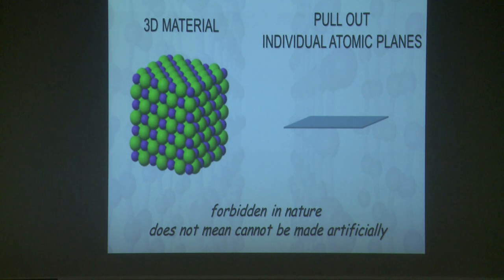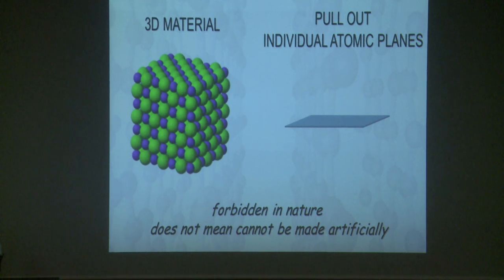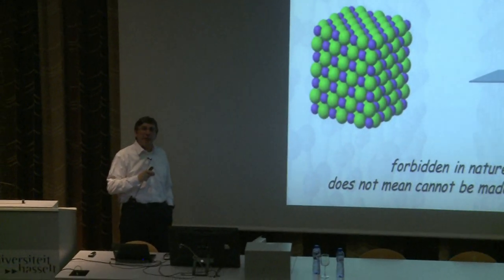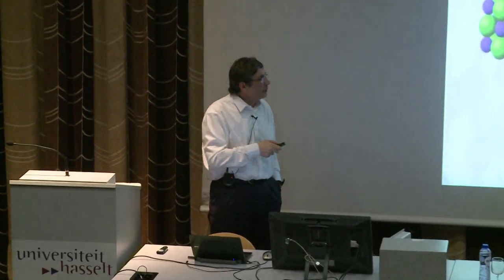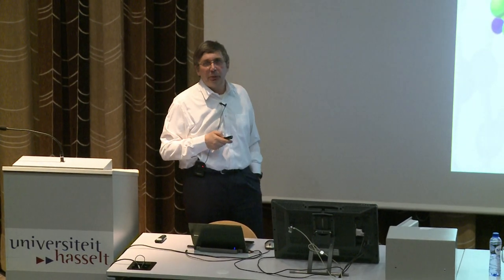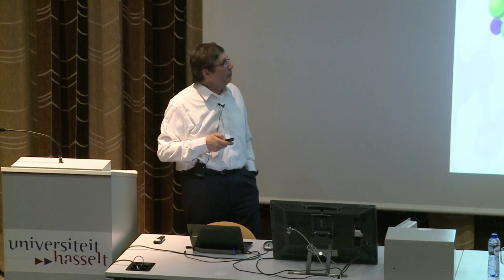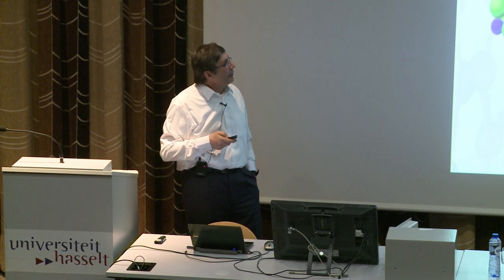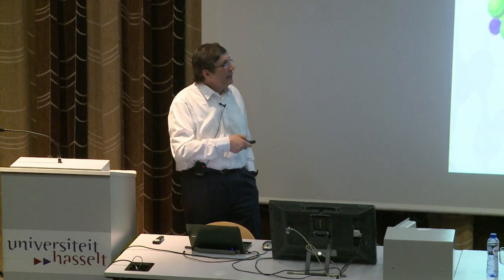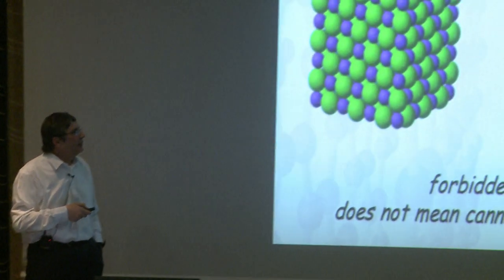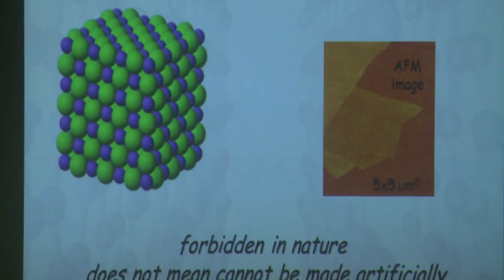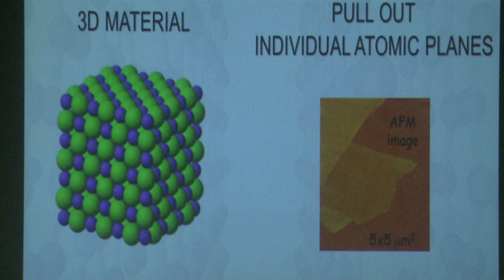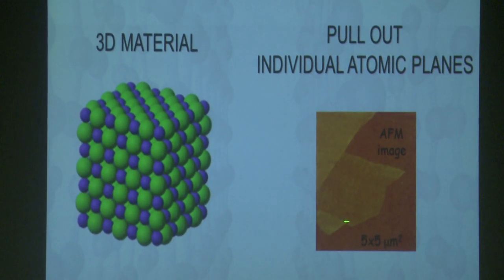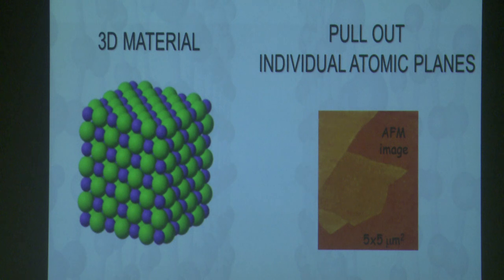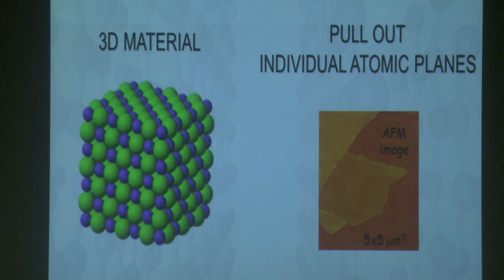That's essentially what we have done in our experiment. We take a material grown at very high temperature, cool it down to room temperature, and then extract one atomic plane. It seems to be very simple, but apparently no one had done this before. Initially, we used some high-tech facilities like atomic force microscopy, and it took real trouble to prove to people that it's one atomic layer. People didn't believe it. People said that it's impossible.